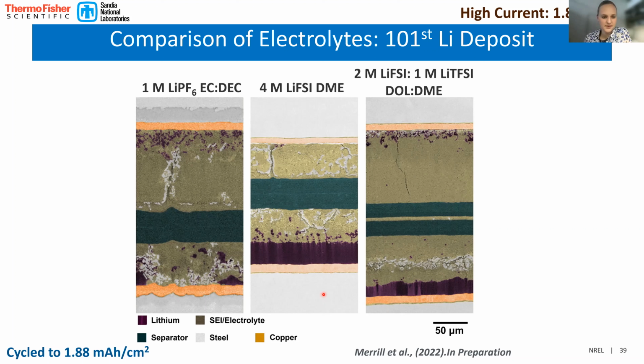In the 4 molar lithium FSI and DME, you can see again there's a lot of lithium inventory left, but there's not a lot of lithium depositing on the working electrode. And then for the concentrated bisalt, under these conditions, there was just a lot of reaction with the electrolyte, and so it's consumed a lot of the lithium and formed SEI.